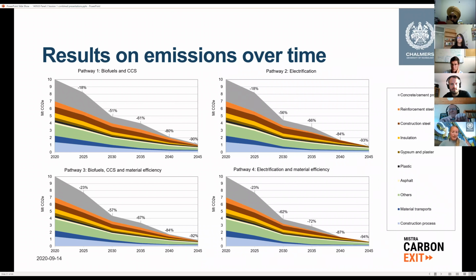And what's interesting is that we see a focus on material efficiency. Of course, I would also note here that we also find, just like Matthias did, that it depends a little bit on where the material efficiency measures come. Do you put them on the end or do you put them on before? In this modeling, you can't see it here, but we allocated it to how much material is used, and then the material efficiency measures first, like we did in the second option, Matthias. And we found that the focus on material efficiency can provide additional reductions, particularly in the short term, which is then a positive measure before we can reach the really deep decarbonisation measures.